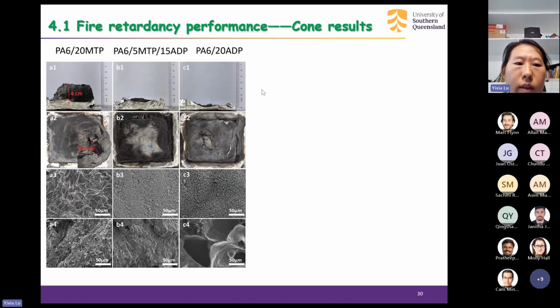We also studied the char layers. For the individual addition of 20% of MTP, the composite left a much swollen char layer with a huge hole here. For the other two composites, we just chose these three typical composites to show the char layers, because we have so many formulas, so many composites. So the typical one, we can see the char is intact and compact.